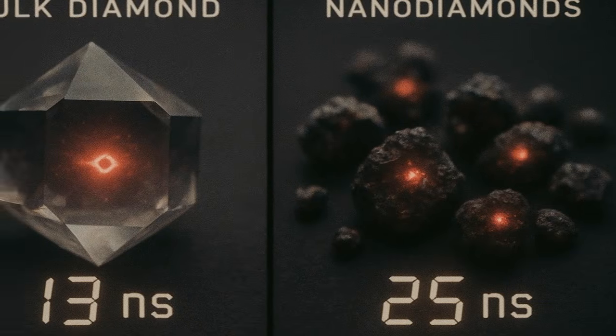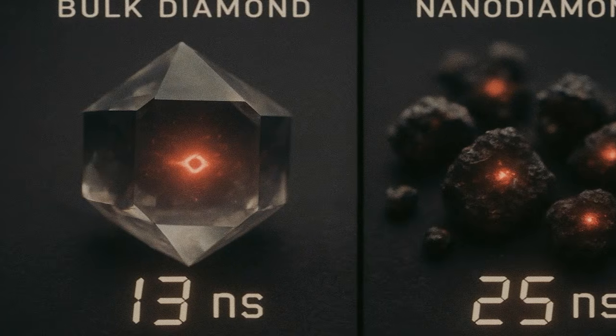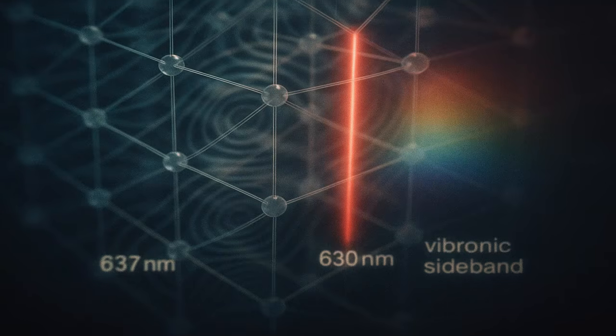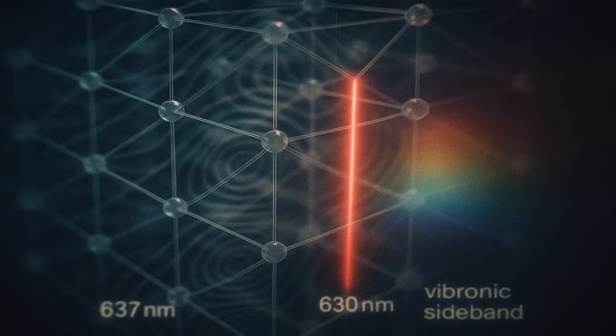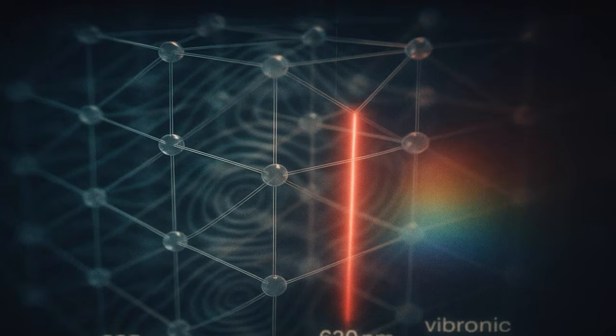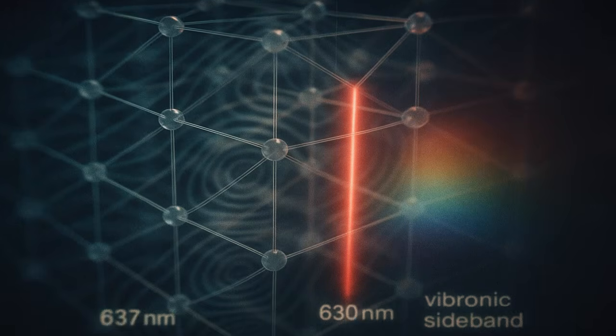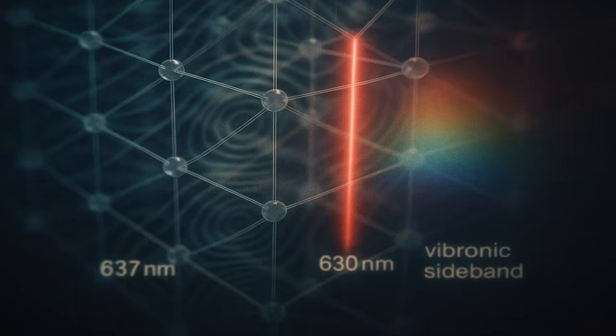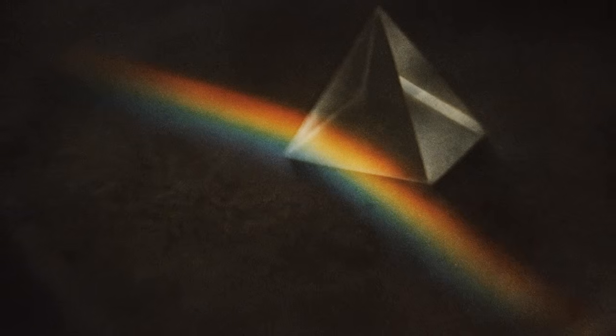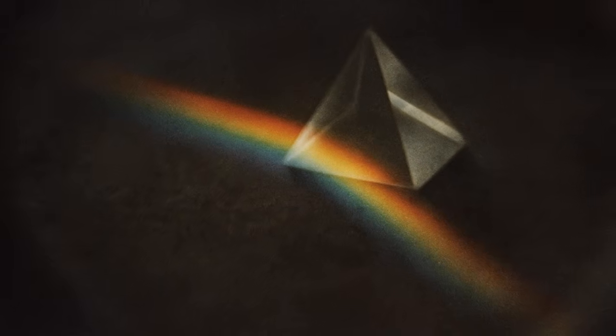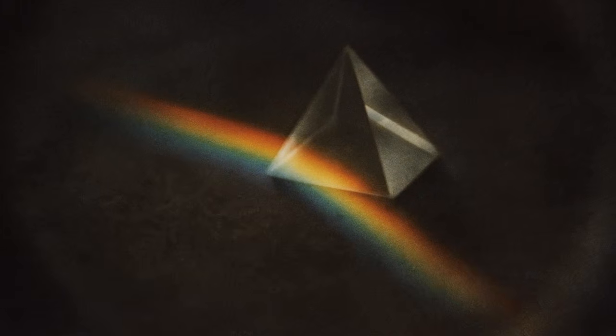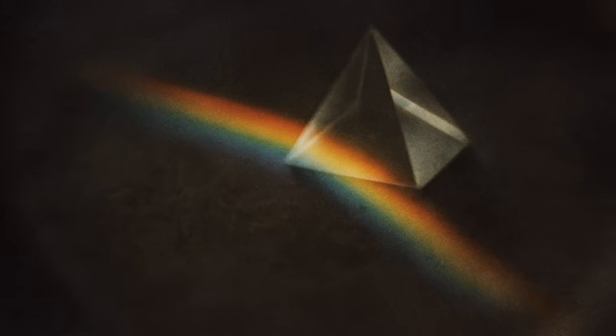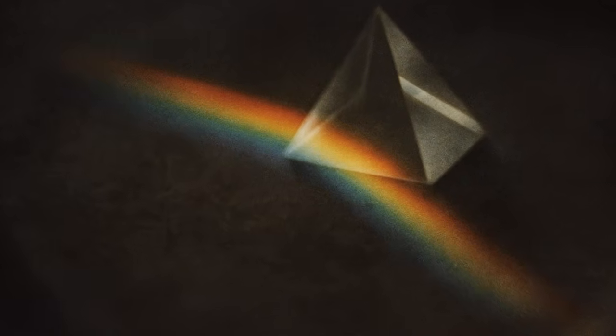The quantum mechanics get stranger. When you hit an NV center with a photon at exactly 532 nanometers, the electron jumps from the 3A2 ground state to the 3E excited state. That's a triplet-to-triplet transition. Spin stays constant. The excited state lasts 13 nanoseconds in bulk diamond, 25 nanoseconds in nanodiamonds, because the refractive index changes how fast light escapes. During those nanoseconds, the electron can do 2 things.